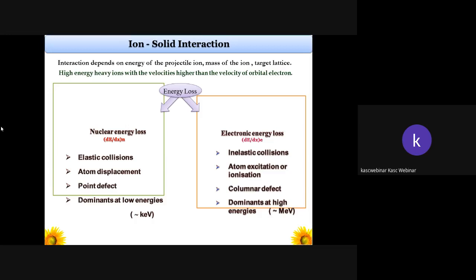By using this inelastic collision, atomic excitation or even ionization can also be possible inside a material, or along the trajectory of the material. Especially if the trajectory is completely ionized and if it is exploded, then it may be called a columnar defect. Actually, this electronic energy loss is very, very dominant at an energy level of mega electron volt.